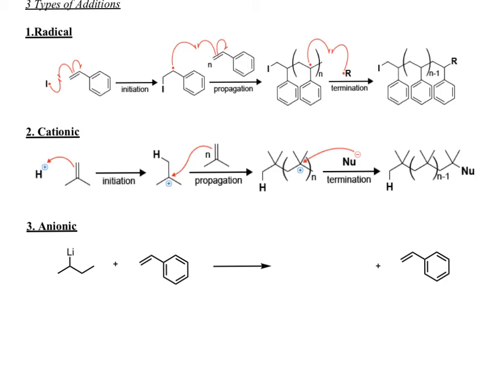And we actually did this reaction in lab yesterday, the advanced folks, this anionic polymerization. So we actually use this called sec-butyllithium. So this is an anion, lithium carbon. You could draw it as this. You had to be very careful with this stuff. This stuff lights on fire in the air. So be careful with this stuff. So it reacts there. Makes a carbanion, so it's like the initiation step. So it's reacting with styrene.